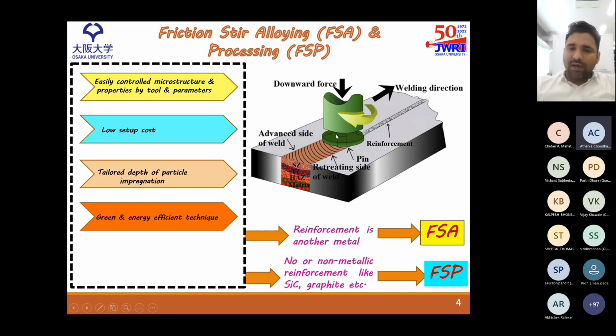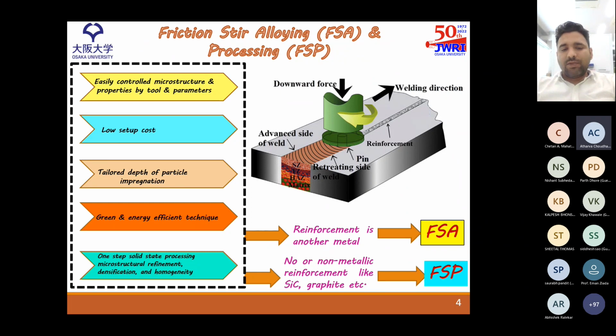This is a tool and it has a pin which is inserted into the base material. So by controlling the pin depth or the pin height, we can easily control the depth of particle impregnation. The process is green and energy efficient as it does not involve any slurry or shielding gases, fumes, etc. And this is a one-step solid-state processing for microstructural refinement. The grains obtained after friction stir processing are very fine. And there are no defects like porosity or gas shrinkage. And the particle dispersion is mostly homogeneous across the thickness, across the shoulder or the processing zone.